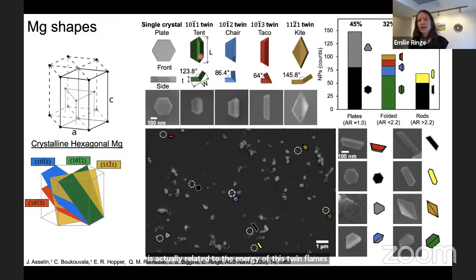So the twin planes in the 101 bar 1 is actually lower energy than the 112 bar 1, and there's just more of it. Disclaimer, we don't know how to control the twinning. We've not been able to do that. If you have ideas how to do that, I would be thrilled, but this is a little bit harder than for gold and silver due to the really pretty harsh reaction conditions.